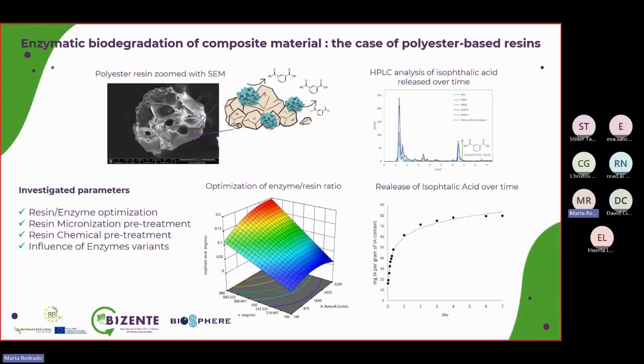In parallel to this production at industrial scale of the enzymes, we studied the enzymatic biodegradation. For this study, 4 different types of resins were covered, and as I already mentioned, the best results were given for the R930, the polyester resin. What we saw is that in this process, one of the main products from the enzymatic biodegradation is isophthalic acid. You can see at the top right a chromatogram showing the increase of the isophthalic acid signal.